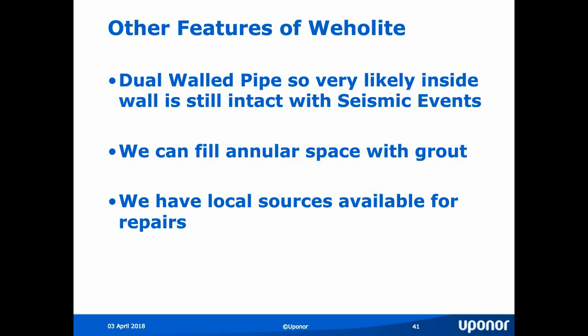As you will see from the other sketches that I have provided in the past, Weholite is a dual wall pipe. So it's very likely in the event that a forklift should hit it or a shovel or something penetrates the outside wall, there's a very good chance that the inside wall will still be intact. So maybe under a seismic event, you may have, for some reason, a rock that shakes up against the outside of the pipe and creates some damage, but it's very unlikely that it would go through to the other side. So there's a certain amount of advantages to using a dual wall pipe for sure.